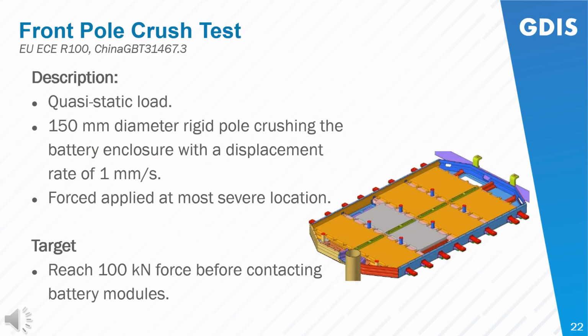Moving on to the nonlinear load cases, we've selected the front pole crush test as an indicator of the performance of the steel construction versus the aluminum construction. The front pole crush test, as indicated earlier, is a quasi-static load applied through a 150 millimeter diameter rigid pole, crushing at a displacement of 1 millimeter per second and applied at the most severe location, with the criteria being to not contact the battery modules prior to reaching 100 kilonewtons.